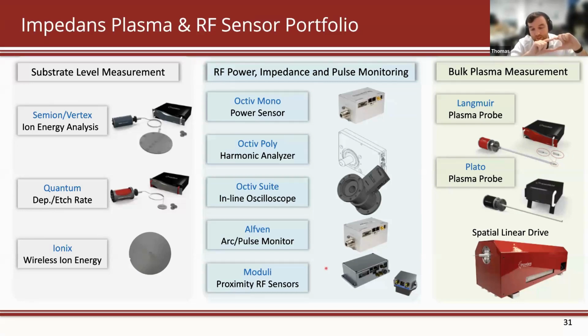That's one reason, and the other reason is at lower frequencies the ions can respond more to the voltage. So that means that you can get the ions to go all the way up to the peak energy, whereas at higher frequencies you're pretty much only going to get the average voltage as the ion energy. At low frequencies you can get all the way to the peak energy, which is going to be 2.8 times the RMS voltage. So you get much higher energies at lower frequencies. So you should use something like we use 400 kilohertz because we have that. We even have Matchbox available at that. You should use 200 or 100 if it's available.